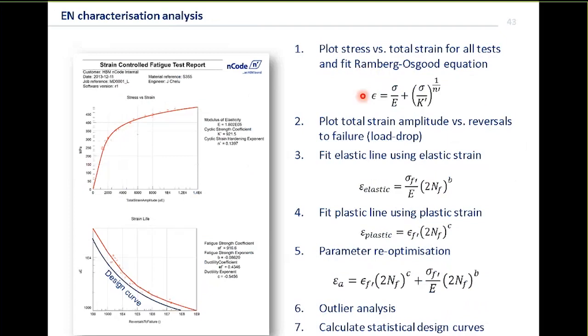What we then do is we find the life based on the load drop, and then we start fitting the elastic line. So we take the elastic strains and we now fit the Basquin equation, the sigma f prime and the b for those elastic. We then take the plastic strains that have separated from that analysis we did before, and this allows us to fit epsilon f prime and c.